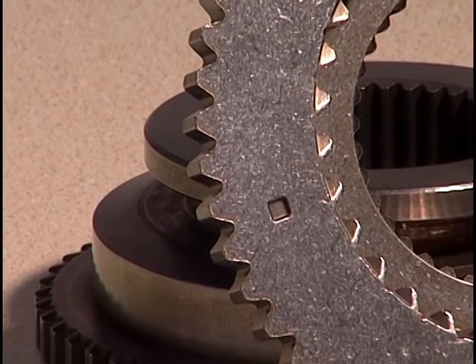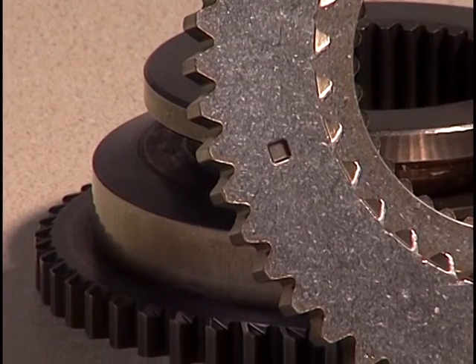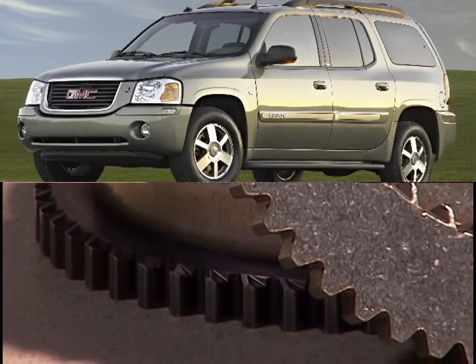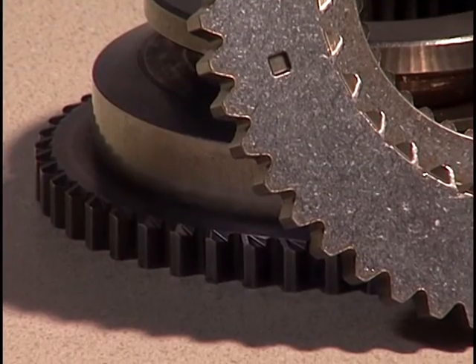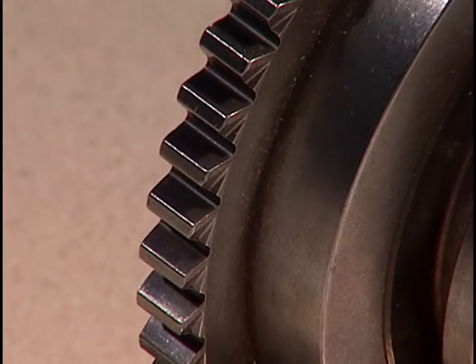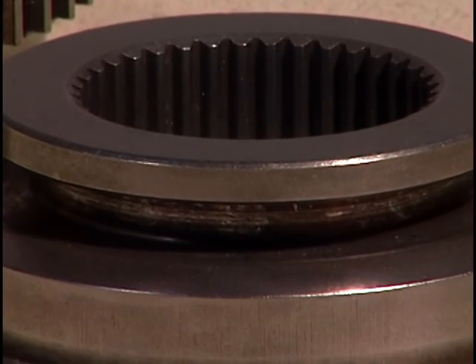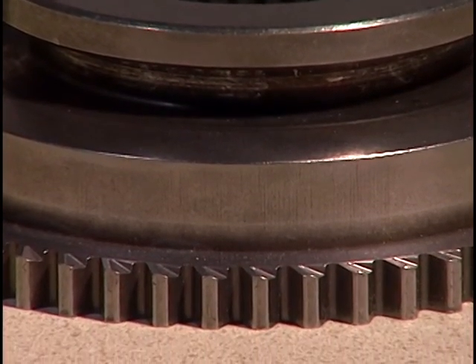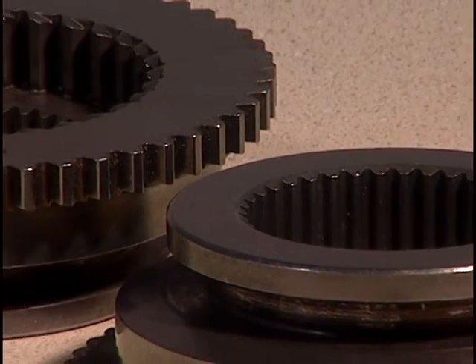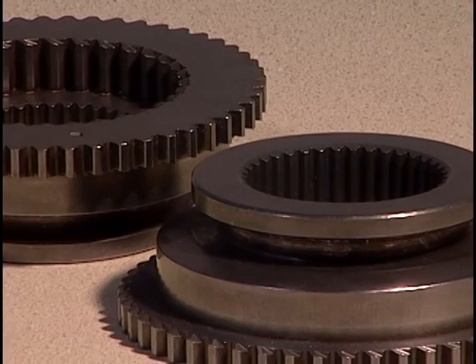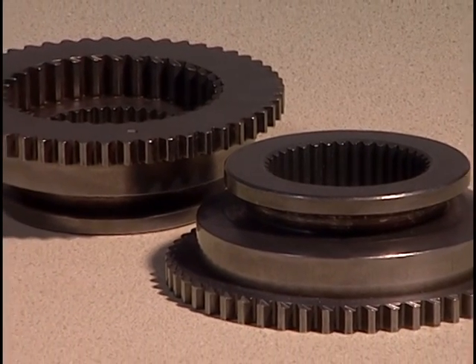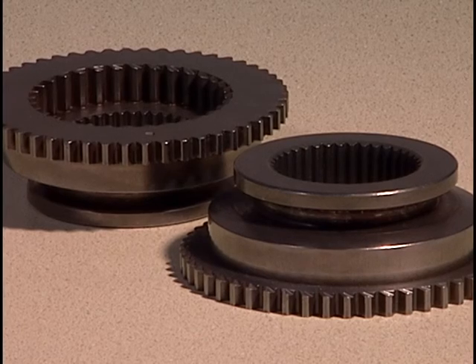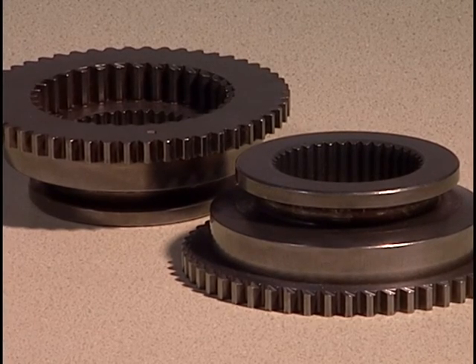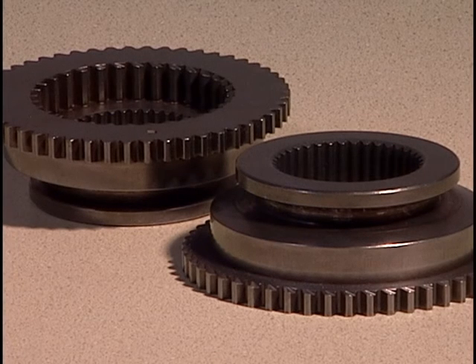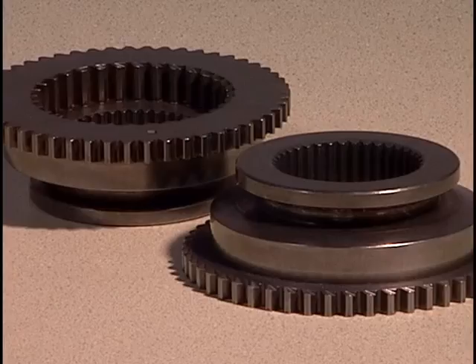This new application for PM, a transfer case differential, is used in the GMC Envoy and Chevrolet Blazer. The part is formed by warm compaction to a minimum density of 7.1 grams per cubic centimeter. All 3 splines are net formed along with the pointed teeth at a minimum density of 7.1 grams per cubic centimeter. Properties include ultimate tensile and yield strength of 180,000 psi and a minimum 35 HRC hardness. PM offered a cost savings of more than 30%.